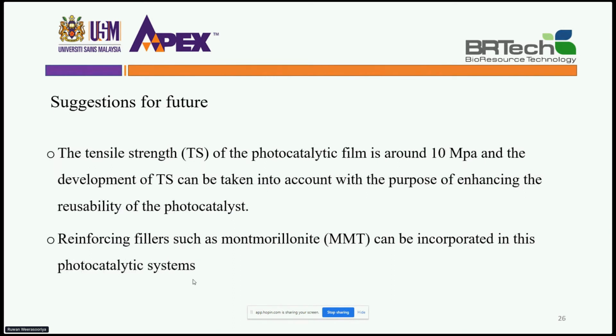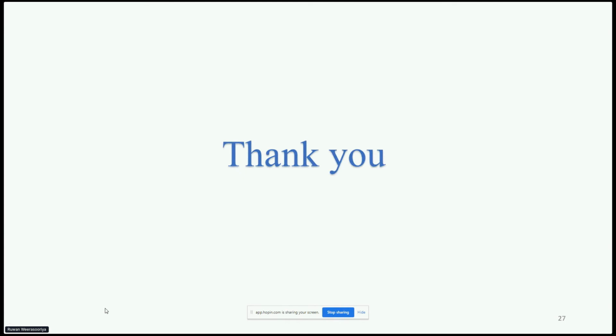So this is a suggestion. Actually, as we observed at the end of the fourth cycle in the cyclic experiment, the catalyst is fragile. That is because of the low tensile strength of the film, which is around 10 megapascal. In future research, it can be taken into account to enhance the tensile strength of the film by incorporating reinforcing fillers such as MMT with the purpose of improving the stability of the film for use for more number of cycles. And thank you.